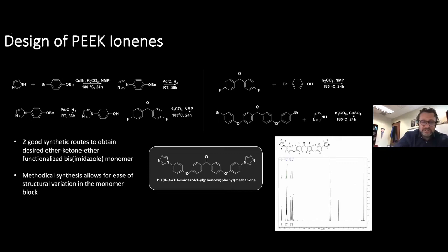Okay, so more recently, I think this is the last one as far as designs. We have these PEEK ionenes, which I showed earlier. This is a little bit different approach, but we've taken some ideas here, and we've made these essentially coupled imidazole phenols to this 4,4'-difluorobenzophenone. This is the classic molecule that's used for polyether ether ketone synthesis. So we can attach those.